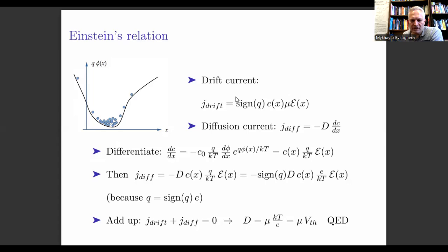So if Q is positive, then the sign of Q is +1, and the drift current density is the product of the concentration of those particles, let's say these are holes if Q is positive, hole concentration times the drift velocity, which is mobility times the electric field. If my particles are electrons, Q is negative, the sign of Q is -1, and J drift, the drift current density, is negative concentration of electrons times mobility of the electrons times the electric field. So this is the drift current. As for the diffusion current, it is the negative diffusion coefficient of electrons or holes times the spatial derivative of the concentration of my charge carriers, dc by dx.